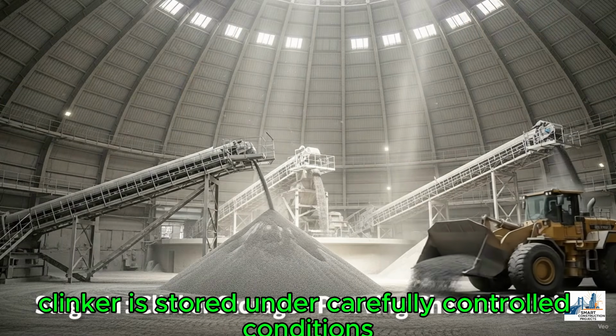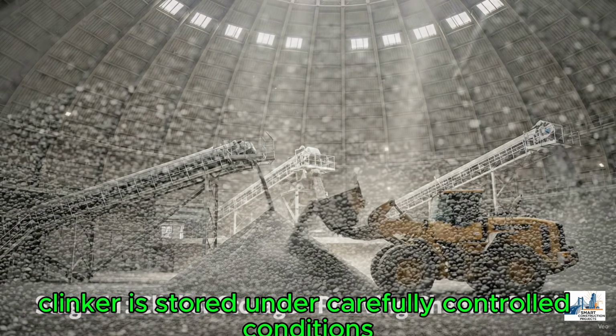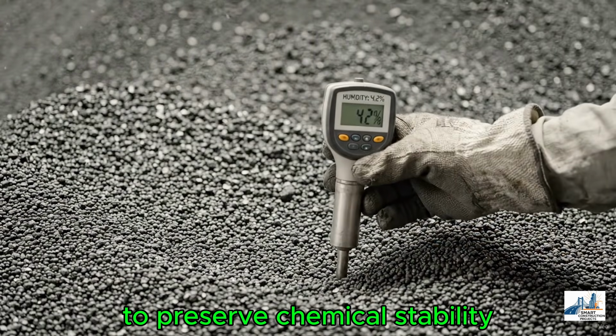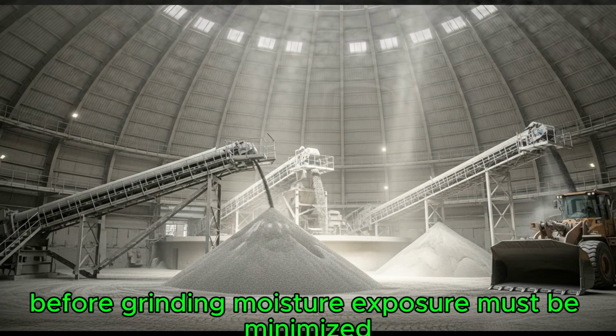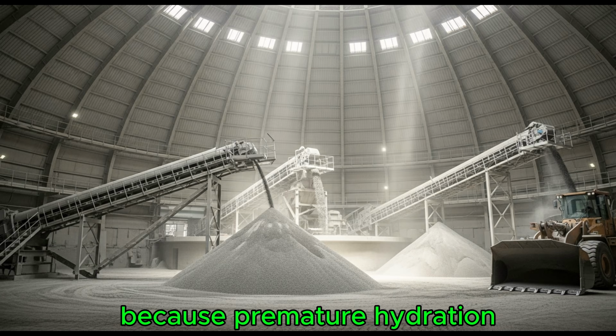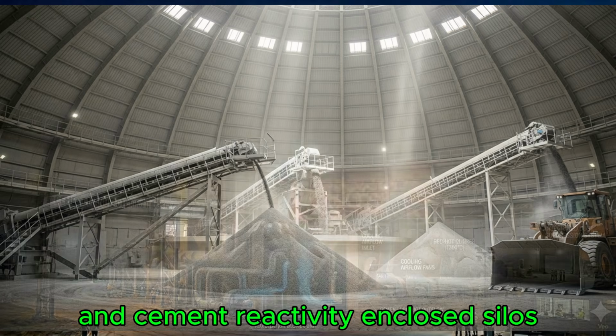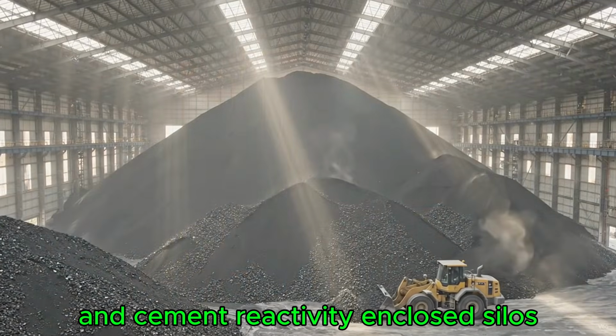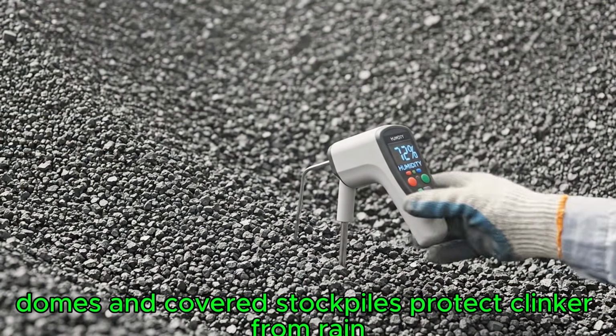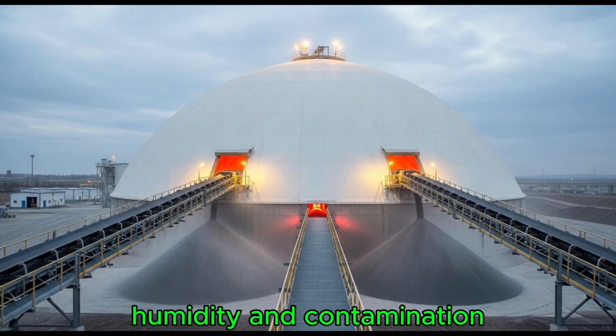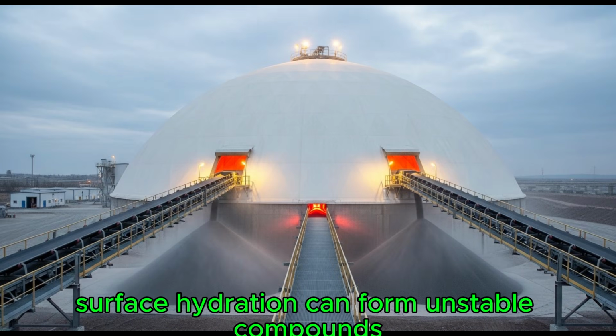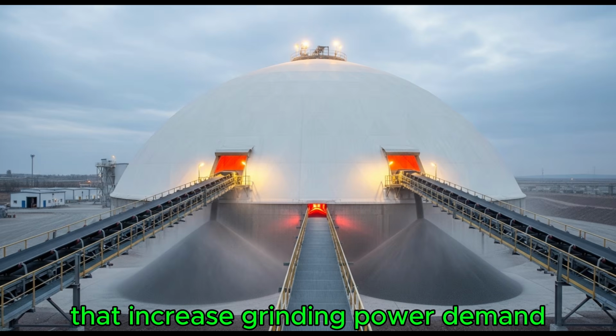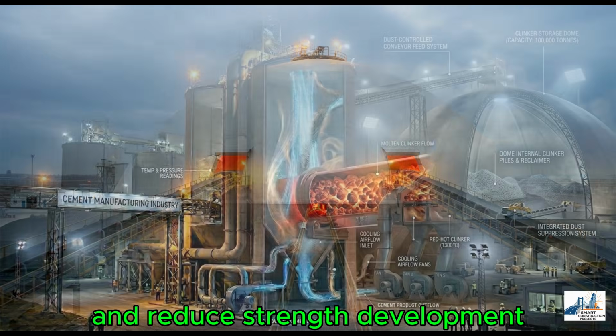After cooling, clinker is stored under carefully controlled conditions to preserve chemical stability before grinding. Moisture exposure must be minimized because premature hydration reduces grinding efficiency and cement reactivity. Enclosed silos, domes, and covered stockpiles protect clinker from rain, humidity, and contamination. Surface hydration can form unstable compounds that increase grinding power demand and reduce strength development.